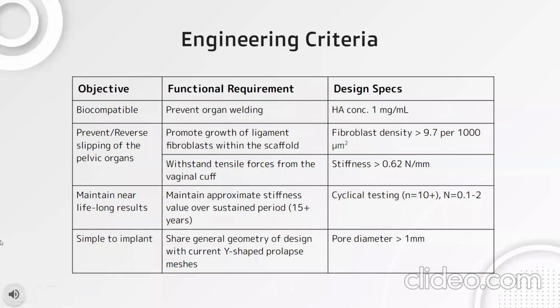Keep in mind the use case of our device. We determined that the following engineering criteria would be appropriate. First, our device needs to be biocompatible to prevent the organ welding that current mesh devices can cause. To do so, our device should have a hyaluronic acid concentration of 1 milligram per 1 milliliter.